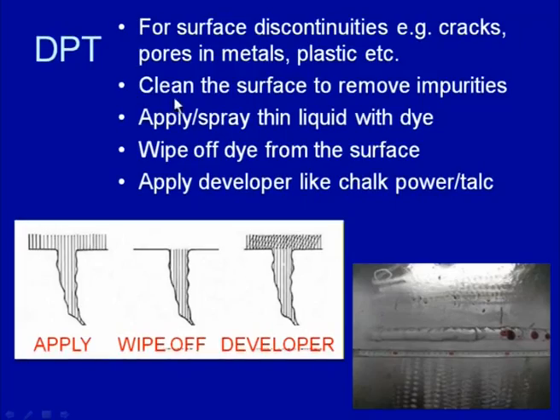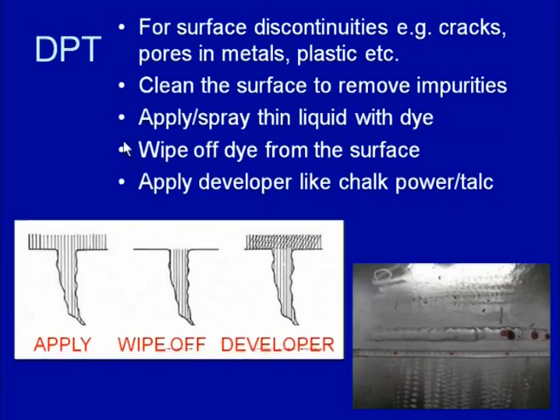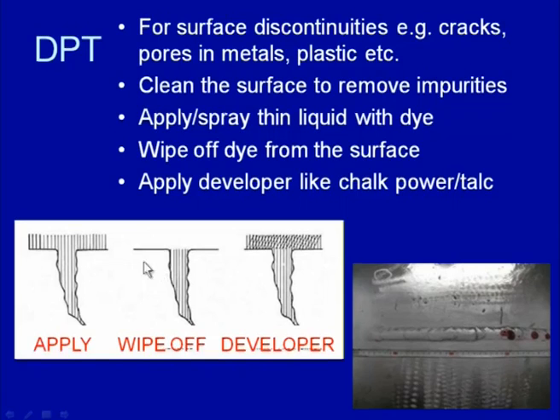So, in this test, first the surface to be tested is cleaned to remove the impurities, and then a thin liquid having very low viscosity and low surface tension, with some sort of dye in it, is sprayed onto the surface which is to be tested after cleaning. Once it is sprayed, the liquid is allowed to stay there for some time, and then it is wiped off.